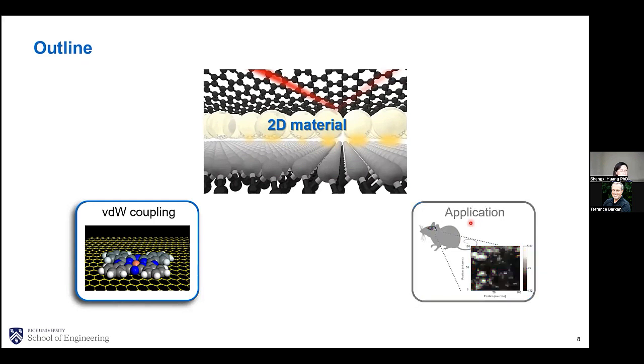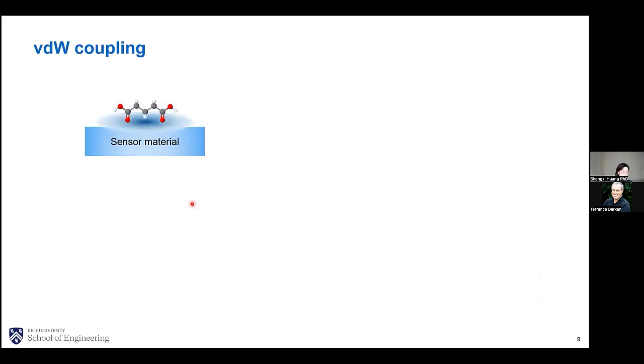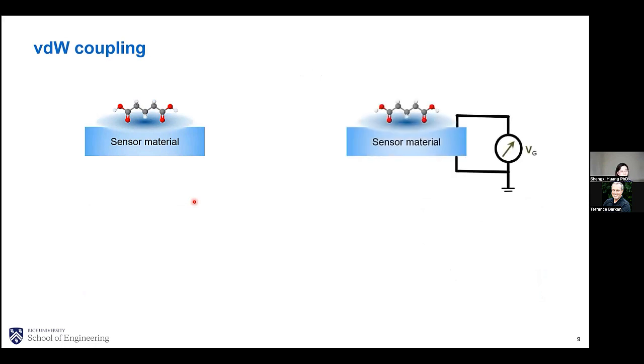So first, let's look at this van der Waals coupling. So if you put a molecule on the 2D material surface or on any sensor material surface, there will be van der Waals coupling between the two. So now the question is, can you further tailor this van der Waals coupling? Of course, one method is to apply a vertical gate voltage. And this gate voltage will introduce a vertical electric field across the surface. And this can potentially tailor the van der Waals coupling. Now, this method requires some non-trivial fabrication techniques. So the question now is whether we can make this a little simpler.